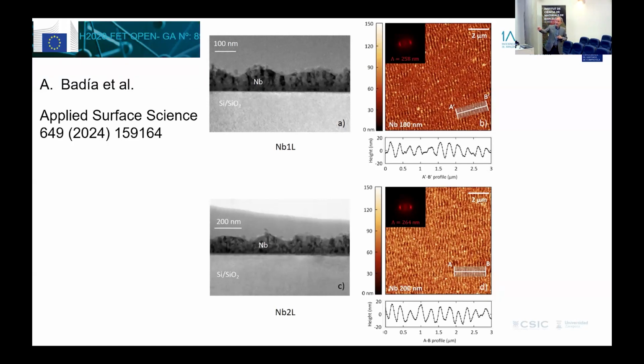So you can see here, this is a lamella observed in TEM. And here we can do analysis. This is the substrate. You can see here that we have not penetrated to the substrate. So we are making these LIPSS, but they are in the niobium superconductor, we have not destroyed it. So this is why we look at this. And also we look at what changes in composition take place with this.